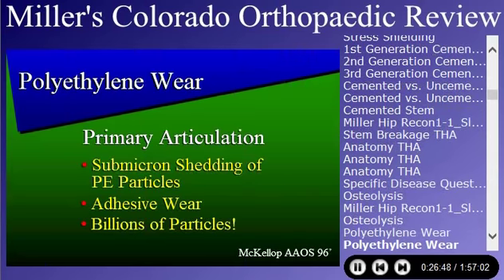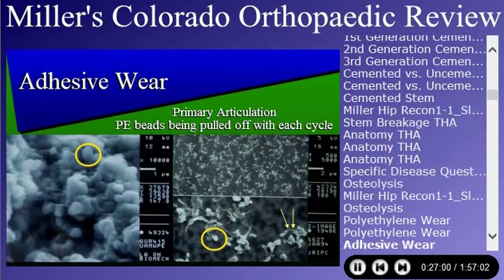If you look at the studies, osteolysis represents the sub-micron shedding of polyethylene particles, not micron particles, but sub-micron particles, a result of adhesive wear generating billions and billions of particles. This is a SEM micrograph of polyethylene. You can see the little polyethylene beads on the left. On the right, you'll see a wear simulator. And at the bottom, those are the little polyethylene beads. And if you magnify it, these are the little beads of the polyethylene on the cup. And at the bottom of the wear simulator, there's those same beads.